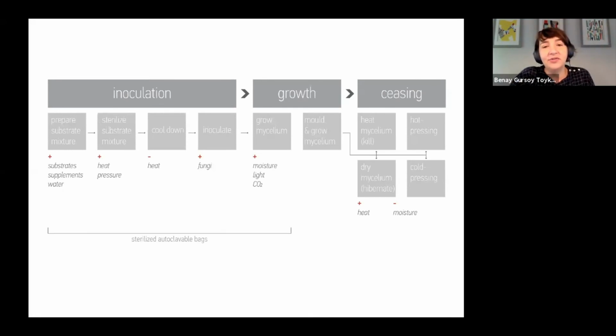And then during the growth stage, we first grew them in bags, and then we created formworks to grow the components. And then there are multiple ways of ceasing growth to obtain the mycelium-based composites. In our case, we dried the components in open air. An alternative would be to heat them, which would kill the mycelium.